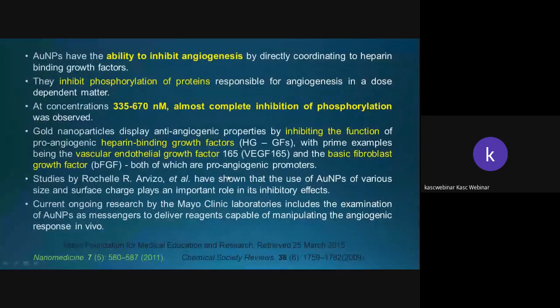So here it's the ability of nanoparticles to inhibit angiogenesis by directly coordinating the heparin binding growth factors. This will inhibit phosphorylation of proteins. Also, in all concentrations, 335 to 670 nanomolar, there was almost complete inhibition of phosphorylation. Why? This is inhibiting the function of pro-angiogenic heparin binding growth factors, HBGFs, and also vascular endothelial growth factors. So the basic fibroblast growth factors, these are all the major ones which can promote angiogenesis. So our gold nanoparticle has a capacity to inhibit the function of these three materials.